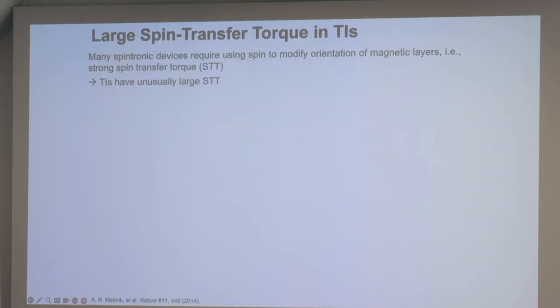And it turns out that TIs are really, really effective at moving spin, basically, because of the spin momentum locking on the surface. So another way to say this is that topological materials have been shown to have very strong spin transfer torque. A spin transfer torque tells you how effective it is at taking the spin in a topological layer and transferring it to a different magnetic layer and rotating that spin, applying a torque from the topological spin on a different material.